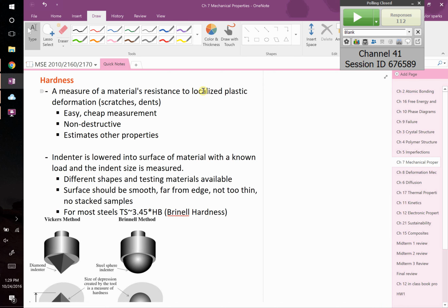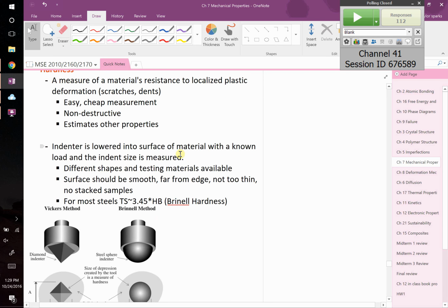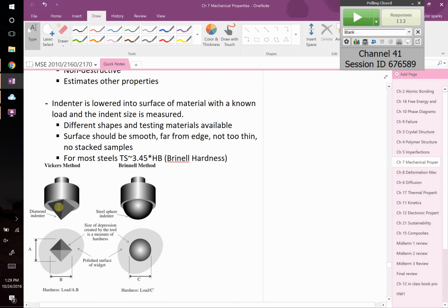Nowadays, we've got much better ways to do hardness tests, but the principle is pretty much the same. You take an indenter, instead of your tooth, you use something that has some prescribed shape. Oftentimes it's a diamond, or if it's Brinell, then it's a sphere. If it's Vickers, then it's a diamond, right? You take that, and under a very specific load, you let it press into the sample. You then remove it, and you either observe how deep it went in, or sometimes they'll actually take a microscope lens and swap it around and look at how big the indent is in terms of area. Either of those can then be correlated to a hardness value, and basically the higher the hardness, the more resistant it is to deformation on a small scale.